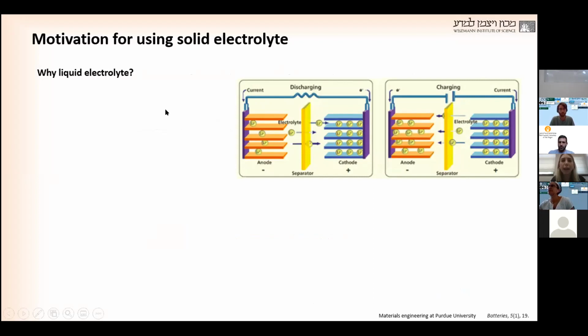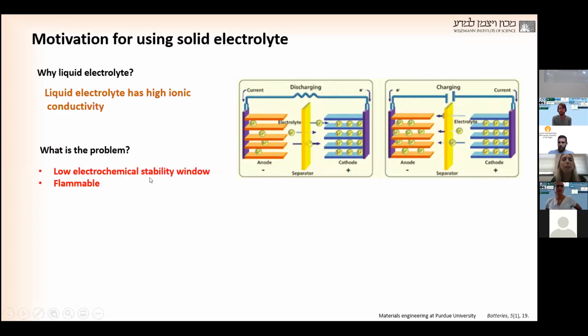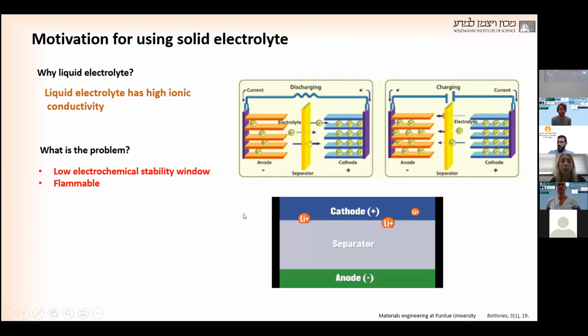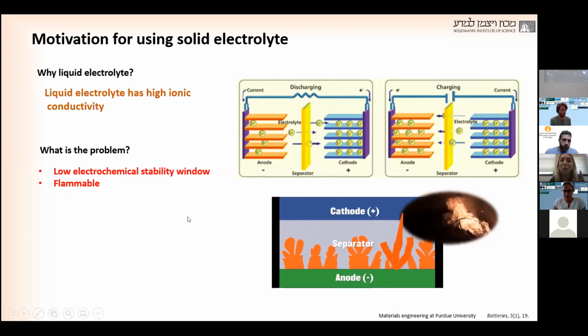So why do we use liquid electrolyte? Because it has high ionic conductivity. But we have a problem with that: it has a low electrochemical stability window. So when lithium ions go to a surface with high energy, they aggregate and create a path called dendrites, which can eventually reach the cathode. And because the liquid is flammable, there is a risk that the battery will explode. So we want a good, safe battery. For that, we will change the liquid electrolyte to a solid one, which is much safer.